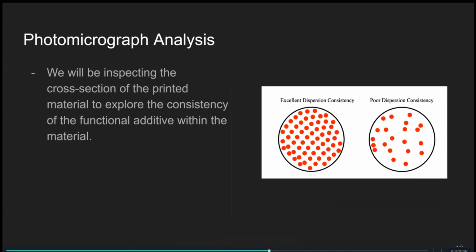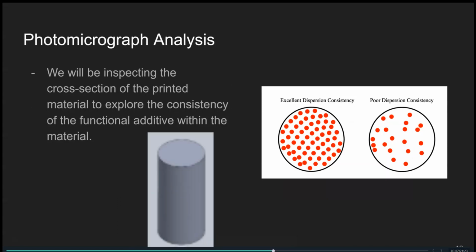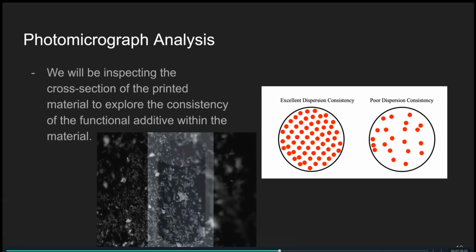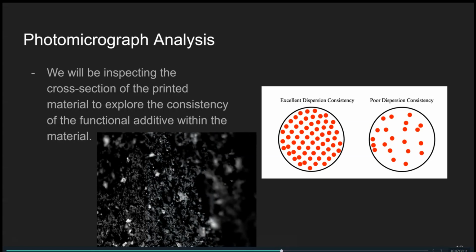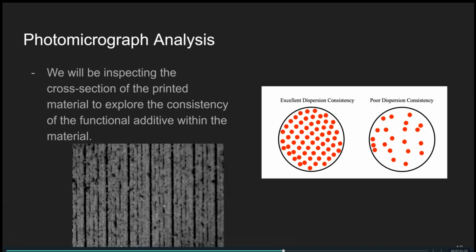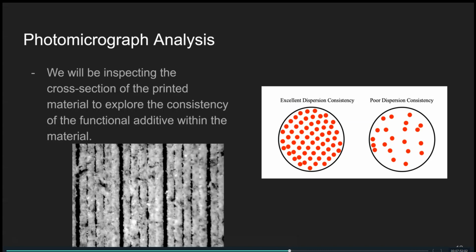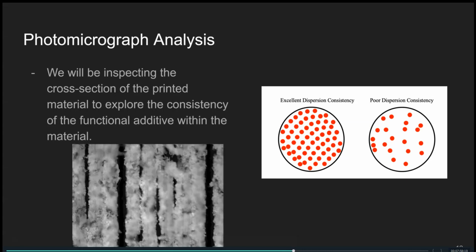The photomicrograph analysis was an interesting test to look at. We were able to see a lot of the differences when it came to layers and the different crystallization of the resin. It was difficult to see the dispersion consistency of the layers since it was difficult to break across purely a layer. We were able to get some pictures of them from the first and the final layer, and then we were able to also observe the cross section in order to see the consistency of those layers. So we were able to extrapolate some sort of consistency throughout the material, but we're not able to directly observe that consistency per layer.